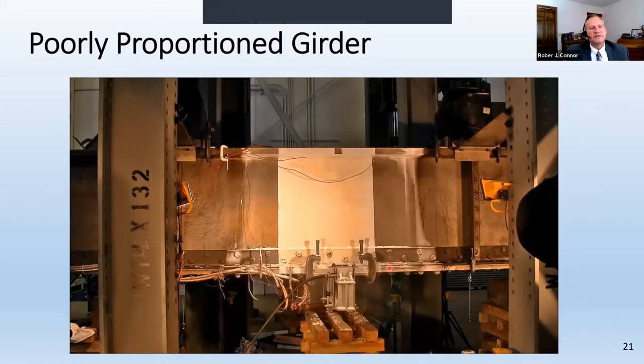That's one of the types of tests. The bottom cover plate here is about 40 millimeters thick, and the angles are about 20 millimeters thick. The point is, this is a poorly proportioned girder, a tremendous amount of energy stored in that cover plate. But as you noticed, when the fracture occurred, the bang occurred, the girder didn't break in half. A whole series of tests were done in flexural members. We've never had one fracture.